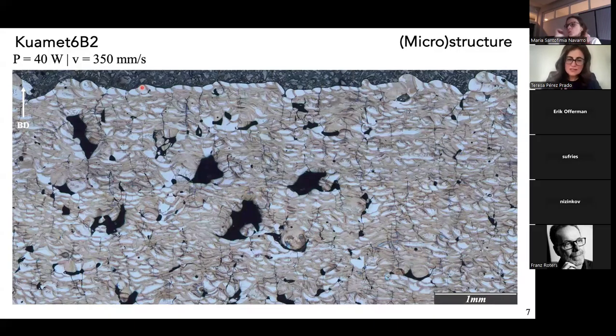So this is just as a first view, optical microscopy for this Kuamet6B2. Here you have the processing conditions. And this is a surface that was polished and etched to reveal the crystalline region. So all these darker brownish regions are the crystalline regions. You see that it's really a composite. And if you look at the top layer here, you see very clearly a cross-section of the laser tracks.